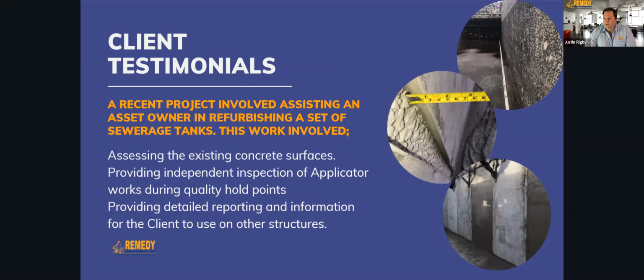The wall at the top right corner is heavily scoured. After it's been cleaned, you can see all the cement matrix is dissolved away, and you're left with that bony concrete with the aggregate hanging out of the wall. So that's reduced the thickness of the concrete. It means that the steel inside the concrete is closer to the surface. There's not much concrete protecting the steel. So in this project, the requirement was to build up the thickness of the concrete using repair mortars.